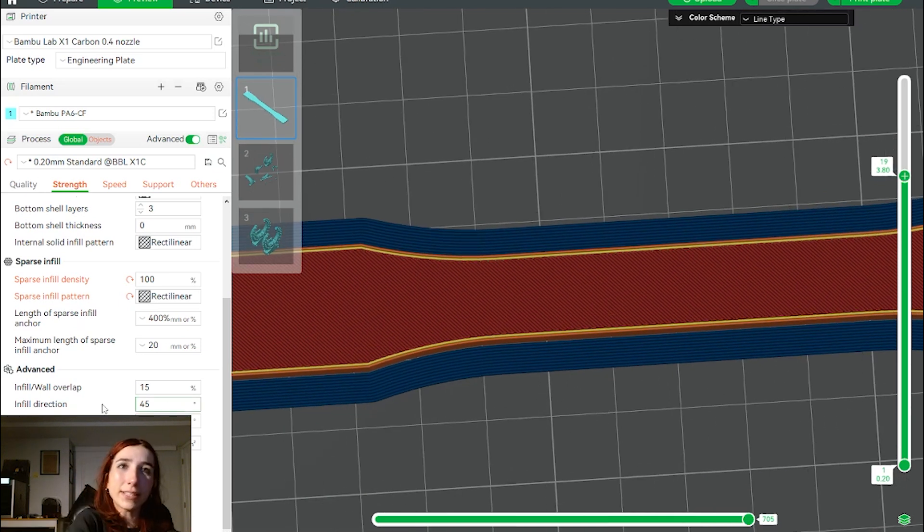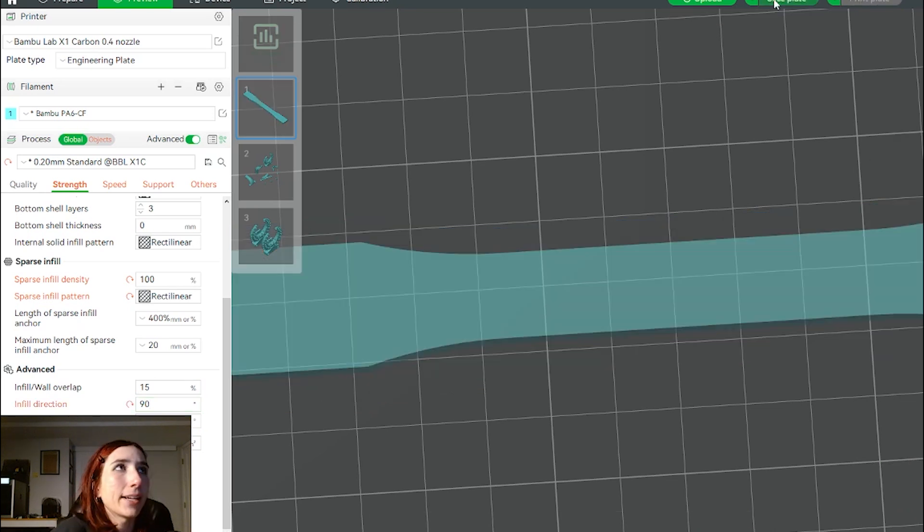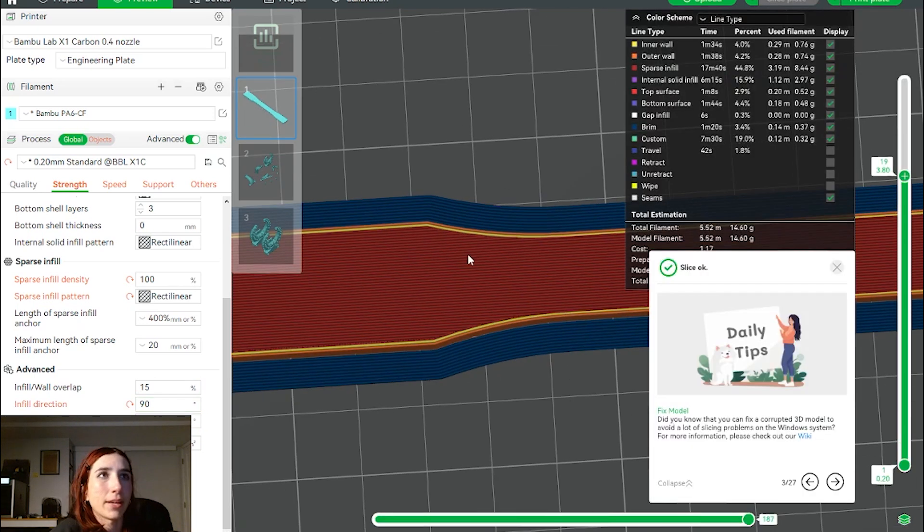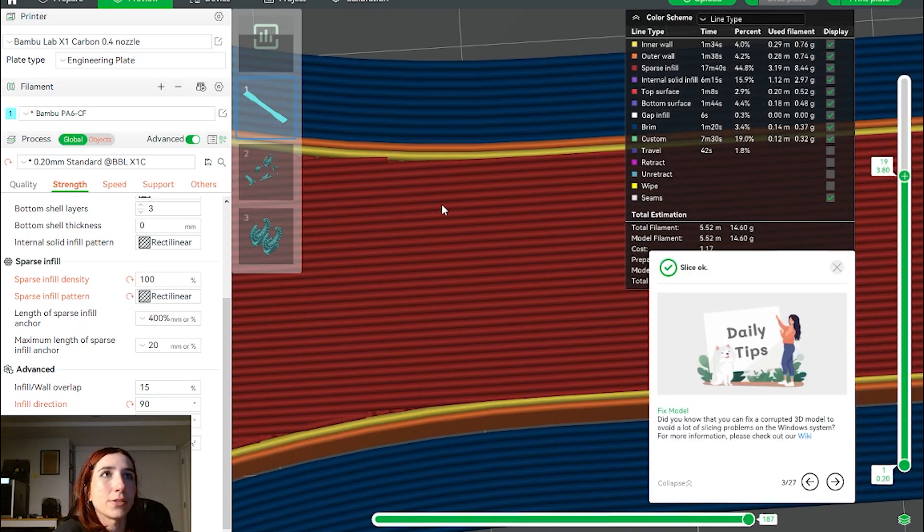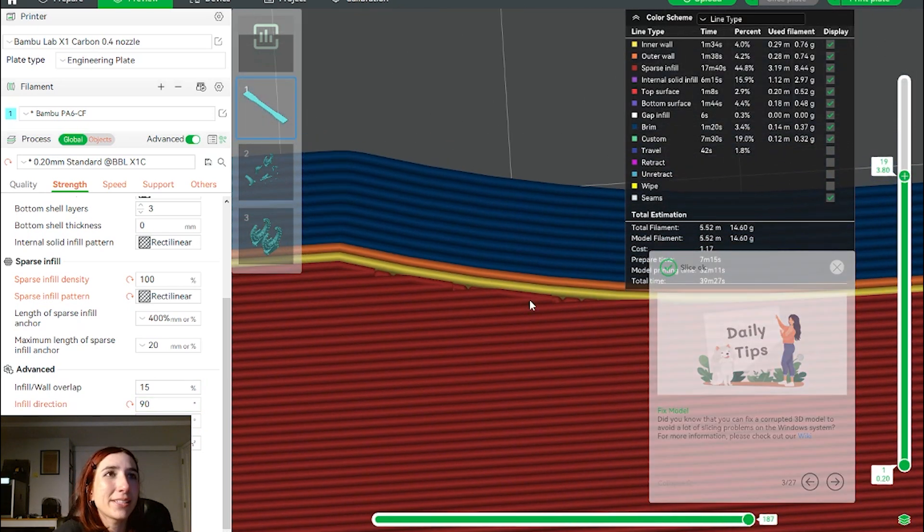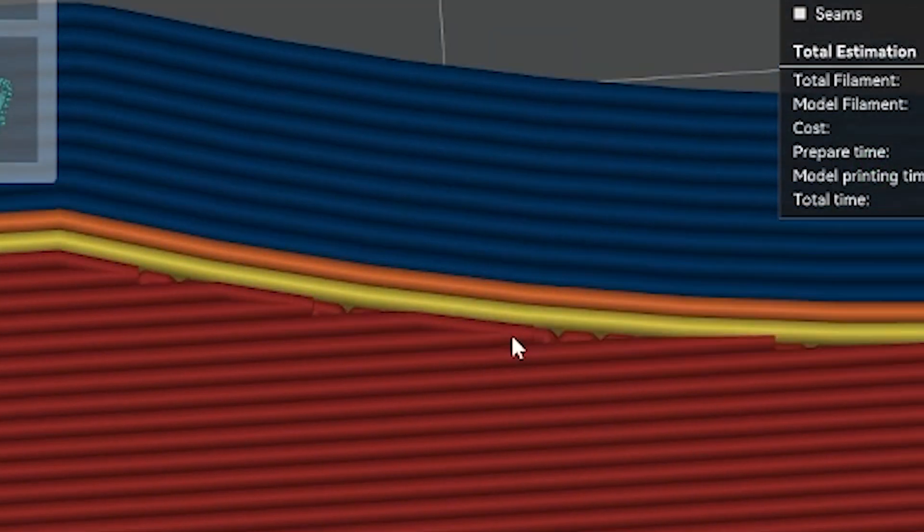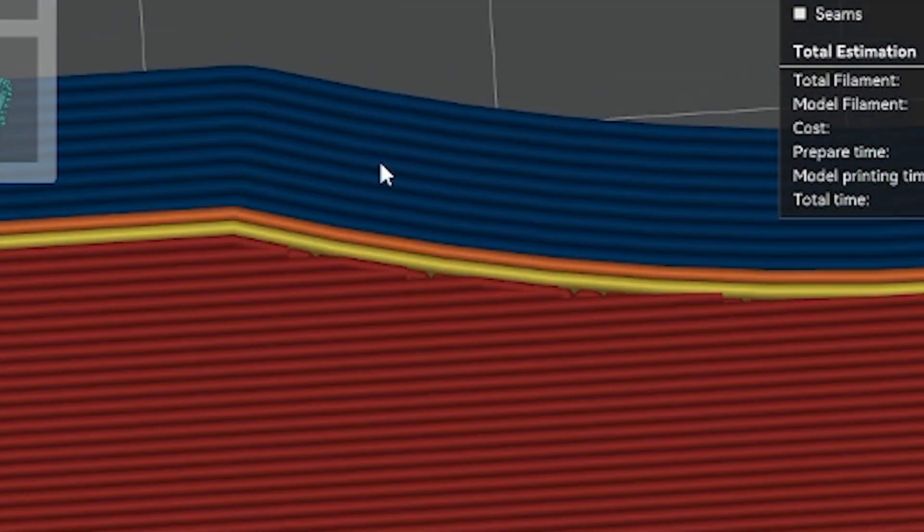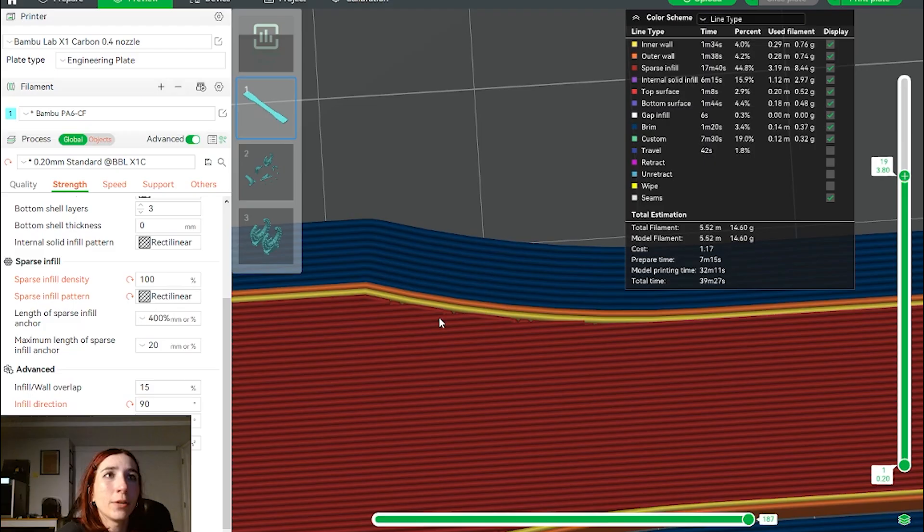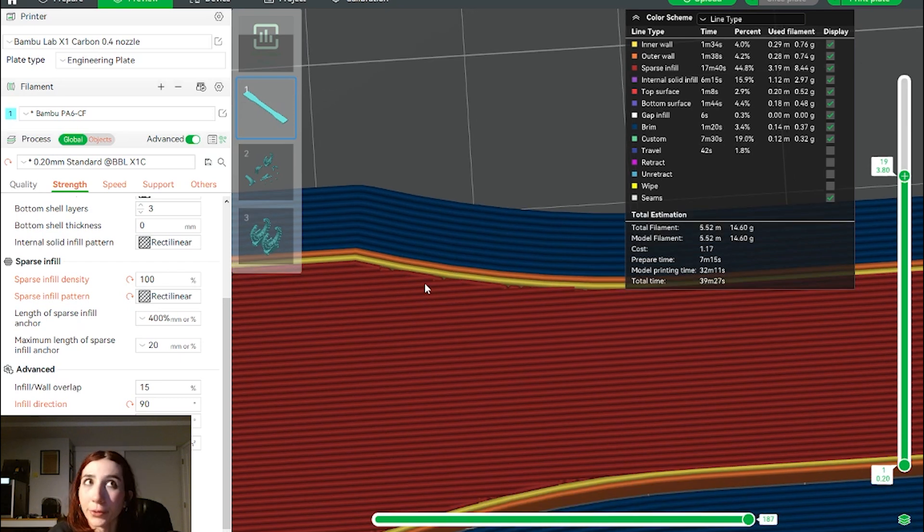An angle that you choose might not be the best angle depending on the geometry of your final part. So let's see what happens when I change my infill to the 90 degrees that I was testing. Hit 90, slice the plate, and then let's zoom in. What we can start to notice is these larger void areas that are in this curved part of the dog bone exactly where my part failed in all five of my tests of this raster and build orientation.